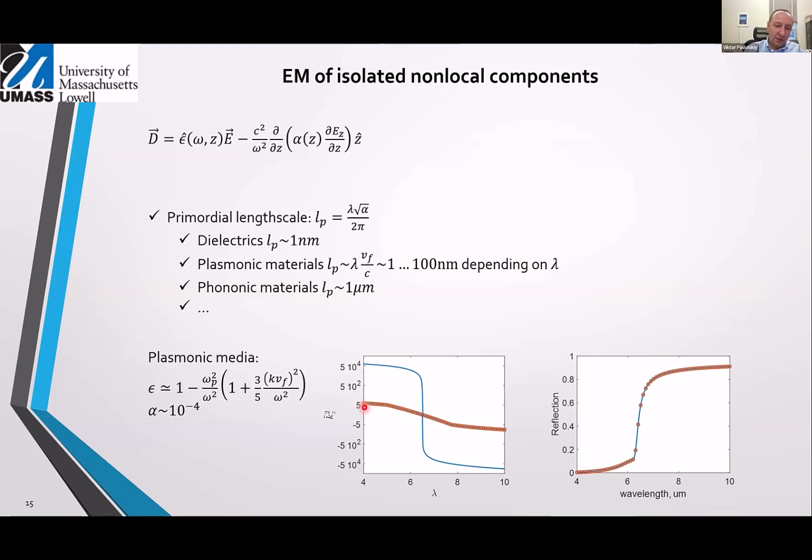And you can see that now instead of one wave, the blue line and the red circles that you see at the bottom, we have a second wave. And so this second mode is the result of adding non-locality to our response. You can see that the second mode has a humongous index, a couple of orders of magnitude larger than the index of your main mode.